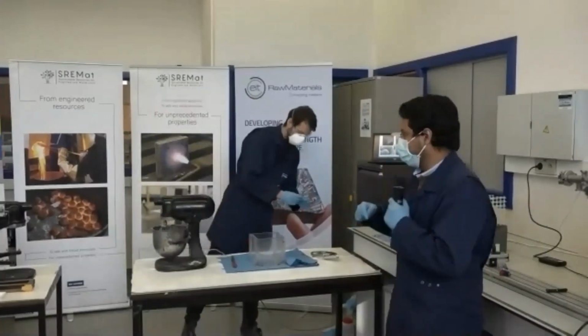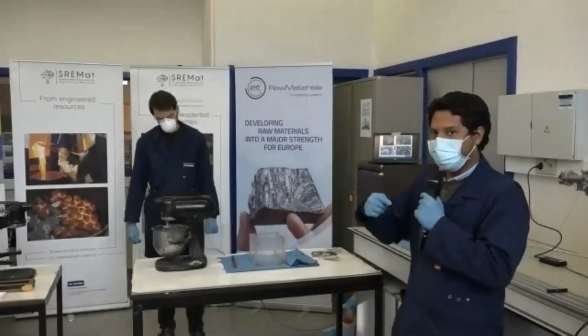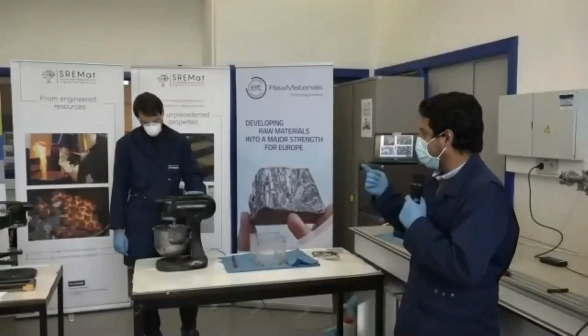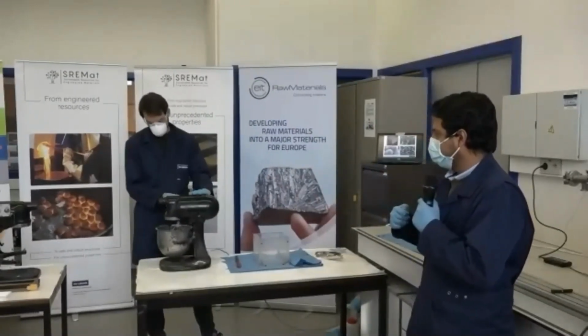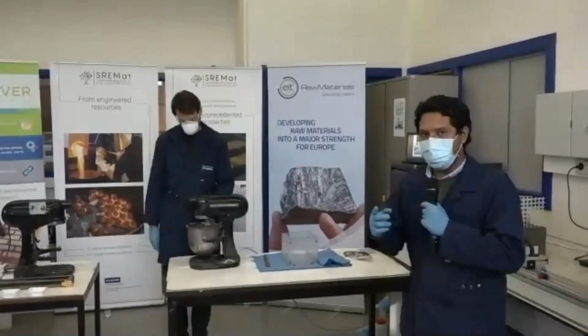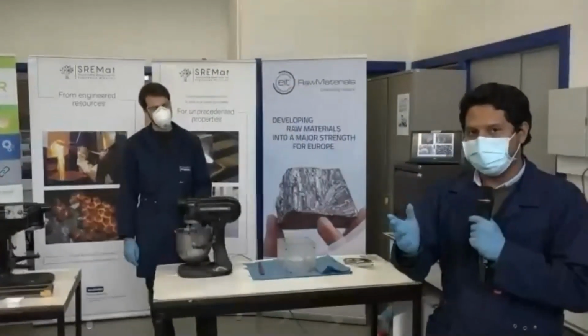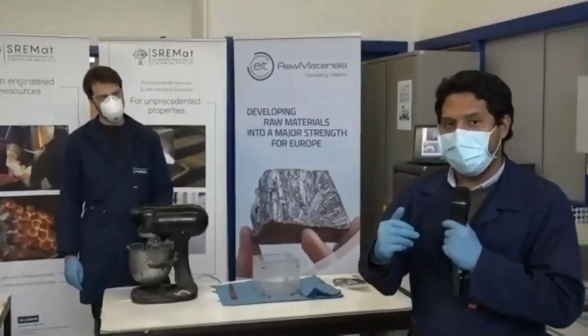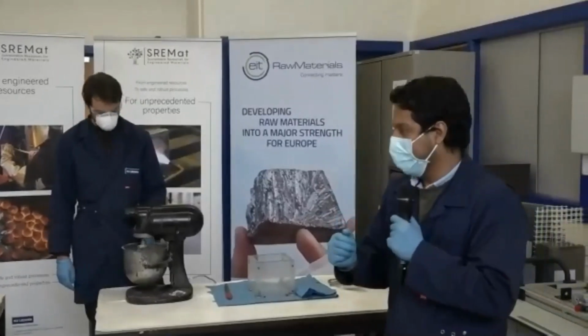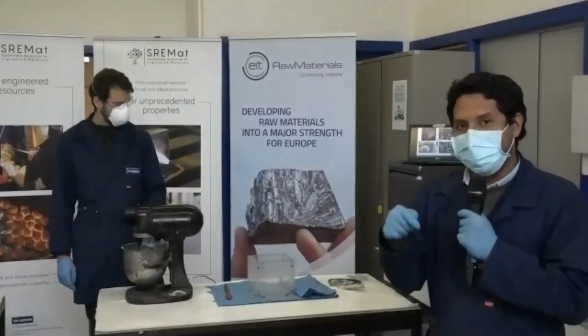So now Tobias is going to homogenize that aluminum within the mixture. He will change it to high speeds. We want to have this aluminum powder all over the mixture. In that way, we can actually create a very homogeneous porous structure later. What is the main reason to add this aluminum inside of the paste?